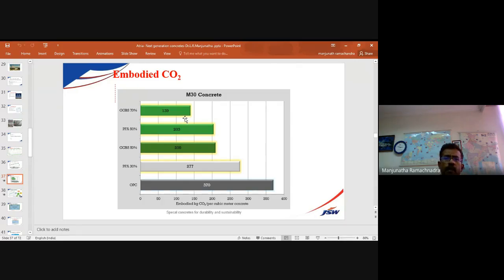Based on the replacement levels of GGBS and fly ash, you can save the carbon footprint. For a pure OPC mix, M30 grade concrete, the carbon dioxide emissions are 370 kg per cubic meter. When you use GGBS 70%, it has come down to 139, about 140. So almost, huge reductions, more than 60%.